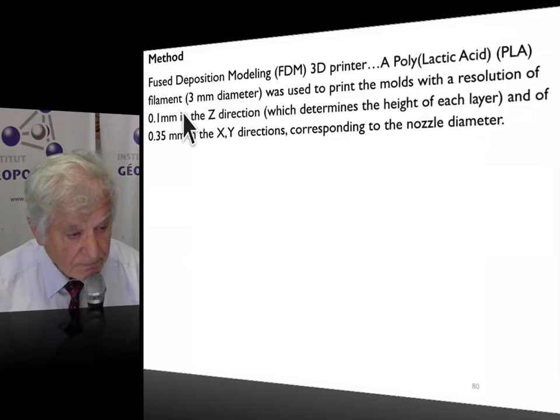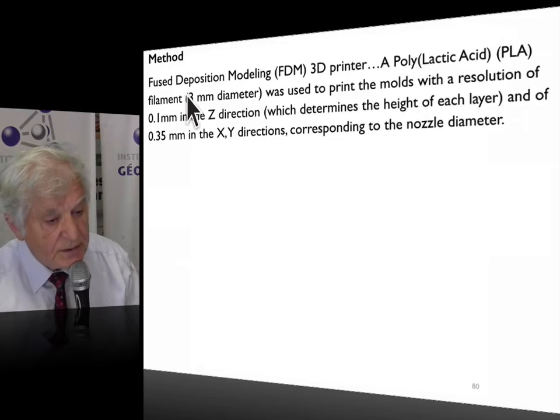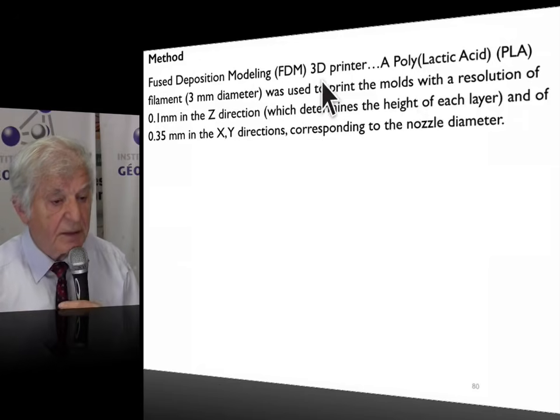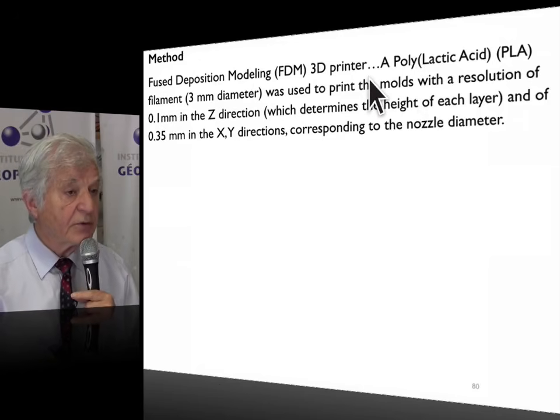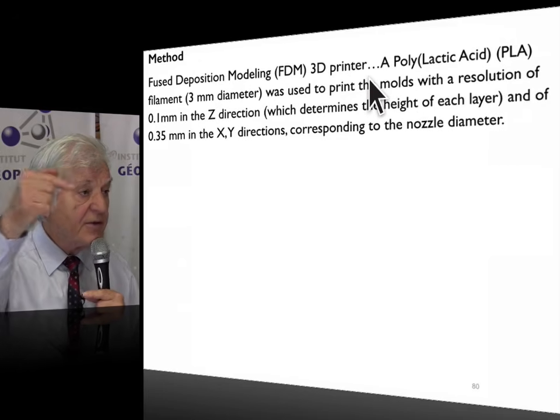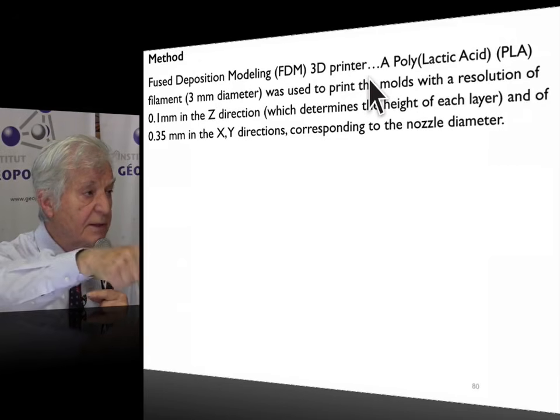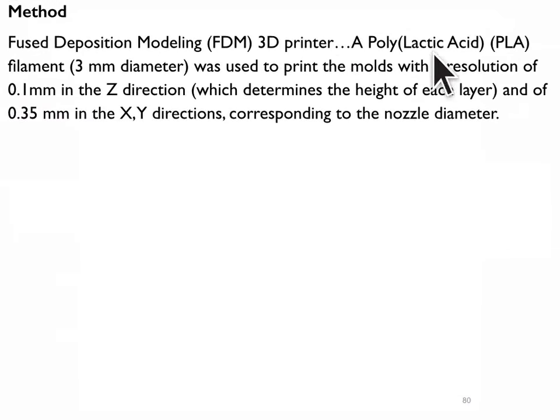Method. They are using a fused deposition modeling 3D printer. You have seen these small 3D printers with a thread that comes through, it is fused and deposited. This is what they have done, but with a very special polymer. This is polylactic acid, PLA, filament, 3 mm diameter, used to print the molds with a resolution of 0.1 millimeters.